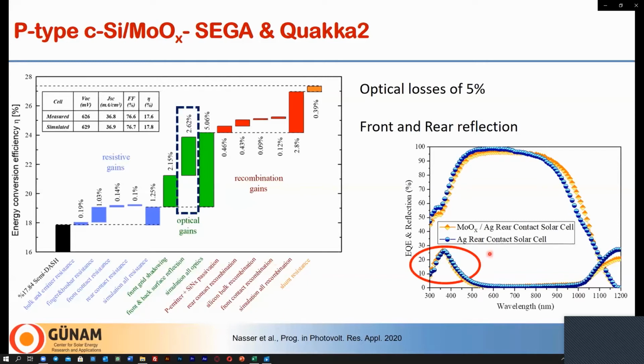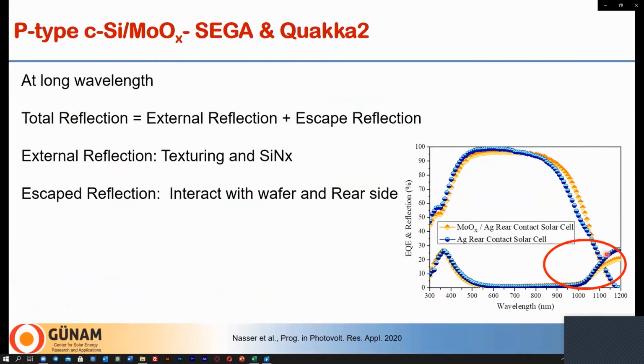So one way to reduce this reflection is, for example, by using double anti-reflection coating, or by using some advanced light trapping interface like inverted pyramid or black silicon. On the other hand, the reflection at longer wavelength is mainly the reflection of the rear side, which is named escape reflection. And it's composed not only from the backside, but there is also some contribution of the front side, like external texturing.